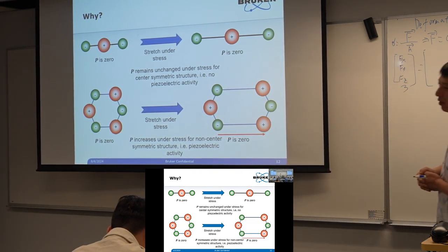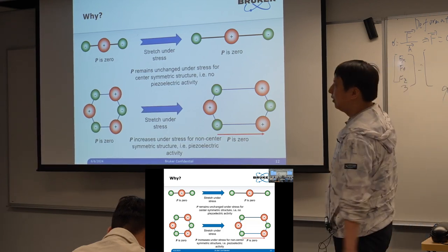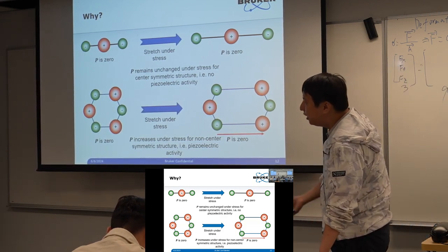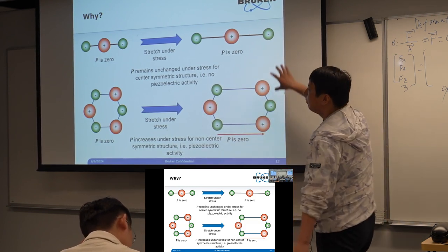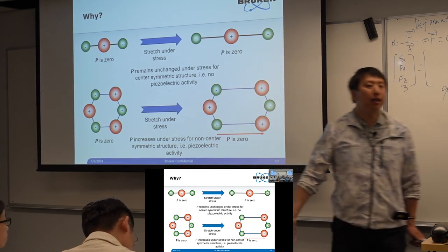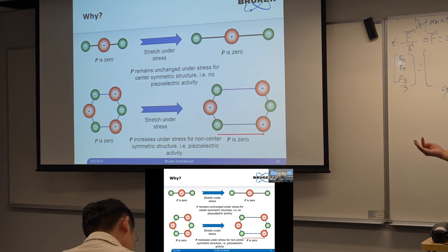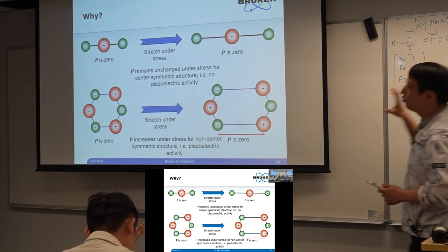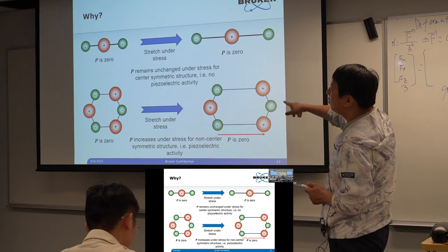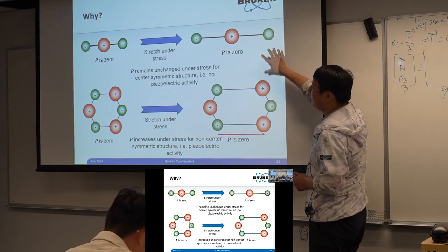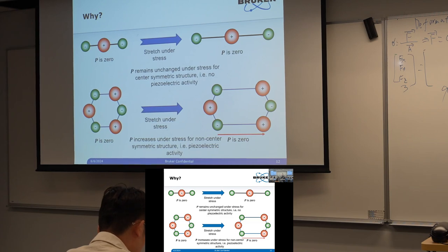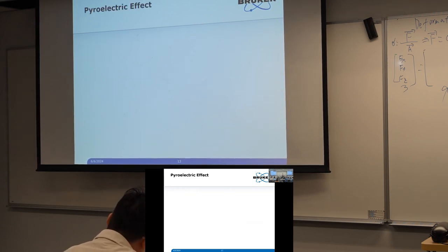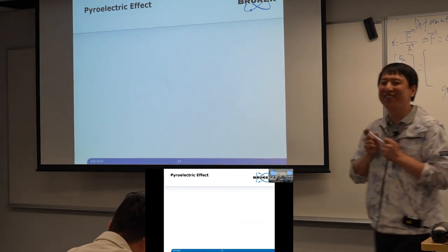If it's molecules, you can do X-ray, you can do infrared, do many things to get the structure first. If it's a crystal, you do TEM, you do XRD first to get its structure. From the symmetry of its structure, you can know if it's piezoelectric or not. Okay? So that's the first thing about our piezoelectricity. Any questions?